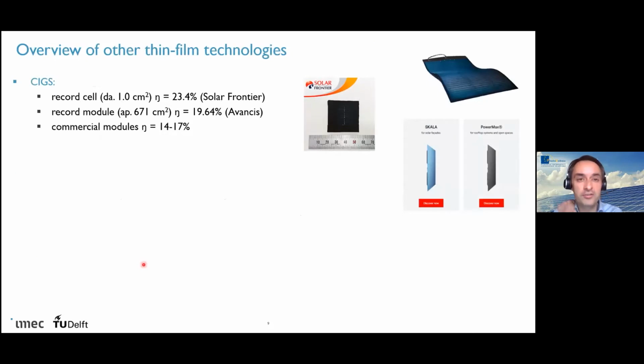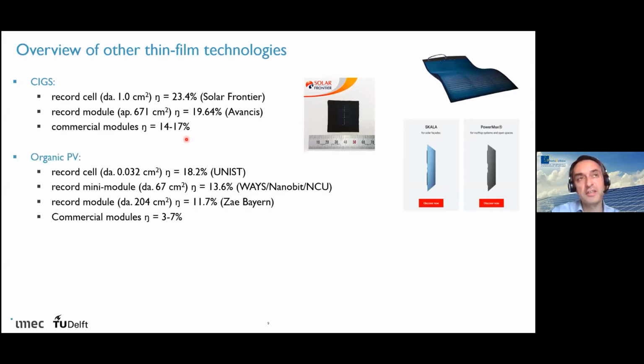Then some other alternative thin film technologies. We have the CIGS that has been discussed in some previous talks. So that's a quite complicated material. You can reach high efficiencies, but upscaling is still a little bit difficult. So commercial modules still have relatively lower efficiency, but there are companies producing this, and the production is typically a few gigawatt per year. People have also investigated for a long time organic PV materials. There, the main downside is that the efficiencies that you can reach are still quite low, but the advantage would be that these can be very, very cheap materials.